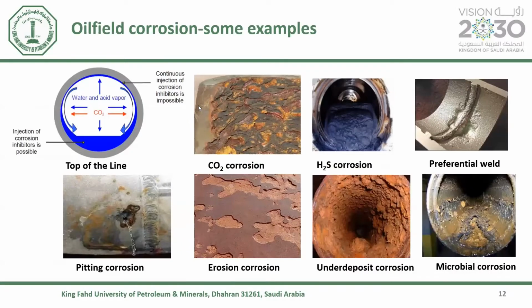Here you have some examples of oil field corrosion. Starting with top of the line corrosion, that means corrosion at the top, especially the 10 to 2 o'clock position of the tubing here, where normal corrosion inhibitor at the bottom of the well cannot really protect the top. Then we have some degradation due to CO2 corrosion here. And H2S corrosion, where you see formation of iron sulfide, which is normally black in color. We also have corrosion at the preferential welds. And pitting corrosion, which is one of the severe forms of damage.